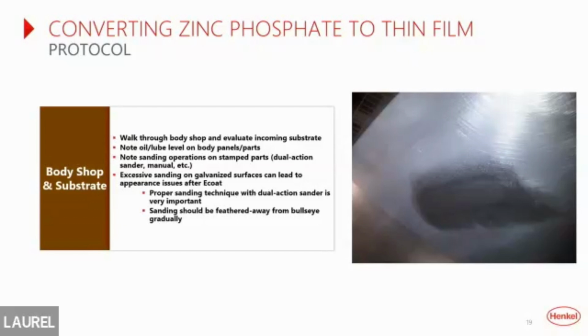And sometimes if it's not done correctly, if you're just taking the dual action sander, digging it in, pulling it away and letting it go, it'll create a hard boundary between the area that's sanded down to that bare cold rolled steel and the surrounding galvanized. If there's a hard boundary layer, that can also sometimes show through the electrocoat after recoat. The proper technique is to feather it. As you're sanding, feather away from the actual middle of the bullseye so that there's not a hard steel versus galvanized boundary.